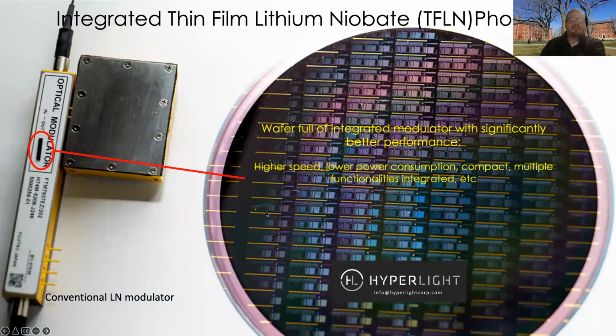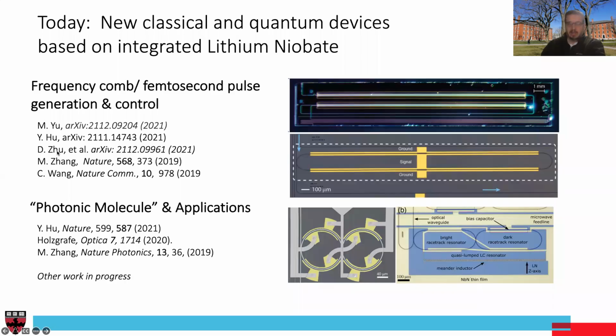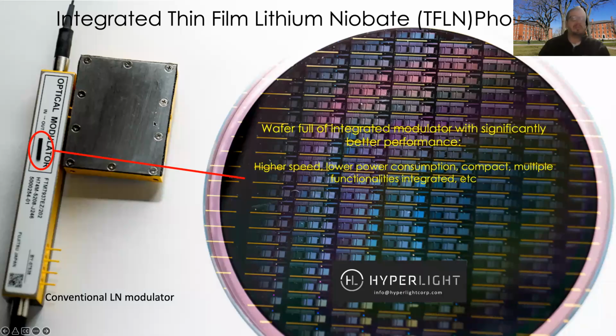Another nice feature is that these devices that I showed you are all realized using conventional planar fabrication technologies. Here we are showing a wafer, I believe this is a 4-inch wafer. These wafers now come in 6-inch size as well. And you can use lithography plus etching to realize a large number of devices. Each of these little chiplets here is one modulator and a bunch of other functionalities. And when you compare this device, for example, to a conventional Fujitsu modulator, you can see that the devices are significantly smaller.